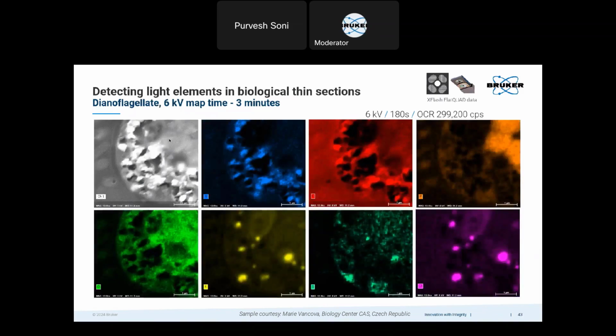And this is a dinoflagellate, so again, a biological thin section, around 100 nanometer in thickness. The problem here was that these bright particles were always seen in SEM, but never in EDS. Conventional EDS was not able to see what material it is. But with the FlatQuAD, low kV, low probe current, only 6 kV and a few hundred picoampere probe current, I could see within a few frames, in a few seconds, that this was clearly nitrogen.